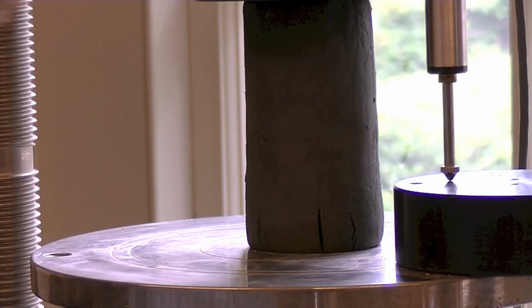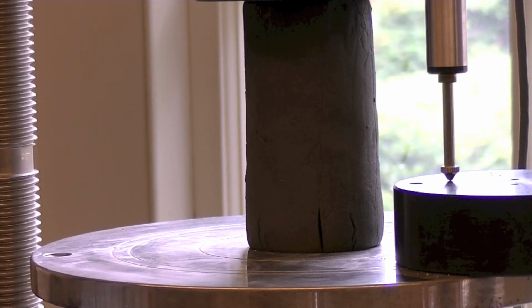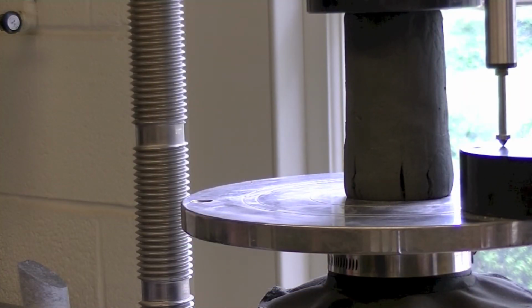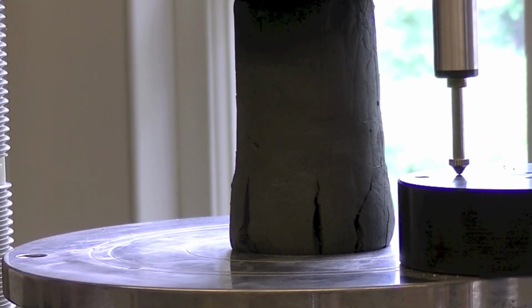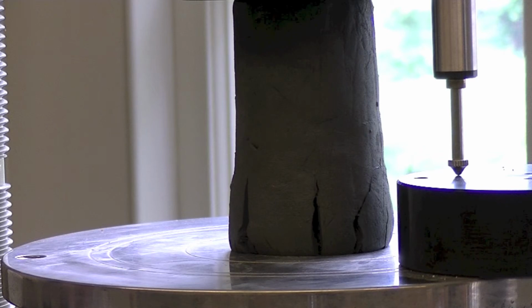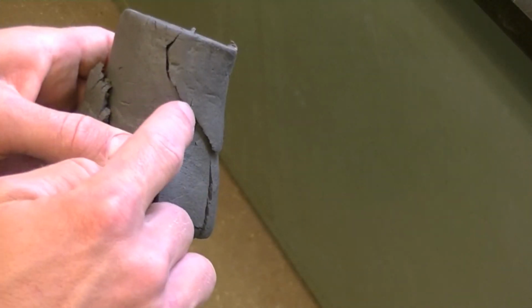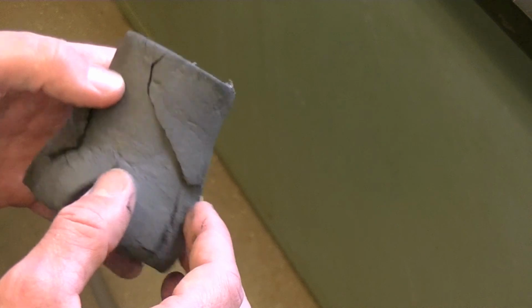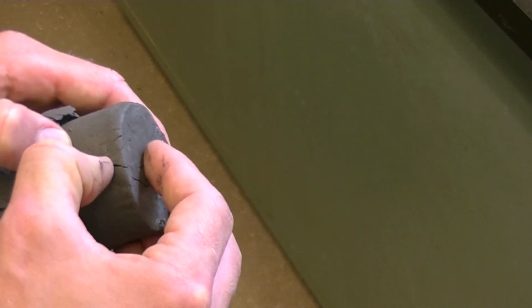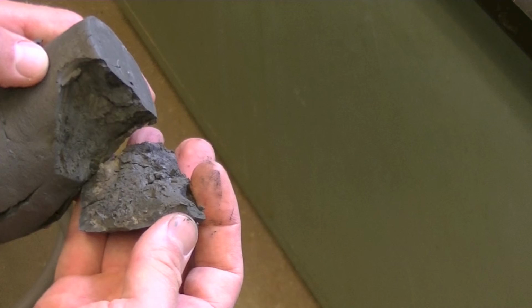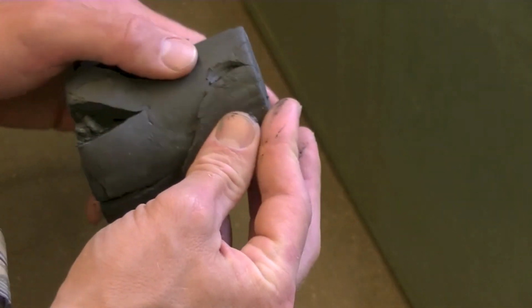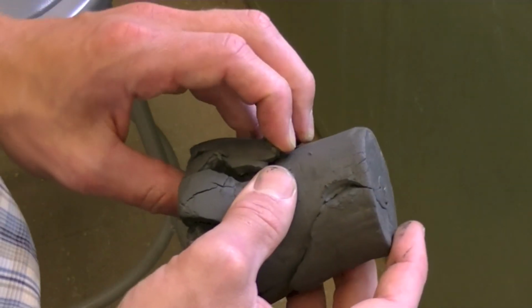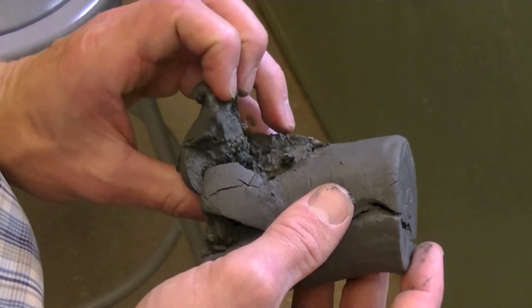Also notice how cracking occurs at the base of the sample. Run the test until the load values begin to steadily decrease. This is a good indicator of failure. In our case, the test specimen was classified as a soft alluvial clay, and it continued cracking before actual failure was achieved. Failure did not occur until shear cracks propagated through the specimen. Then load values began to decrease. Notice the two shear propagations on top and bottom of the specimen. These are the natural failure planes. Cohesive soils and rock will display such failure planes when failed in compression.